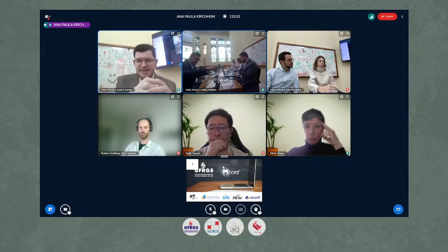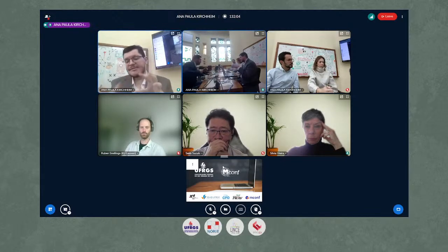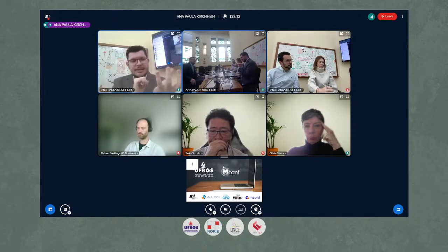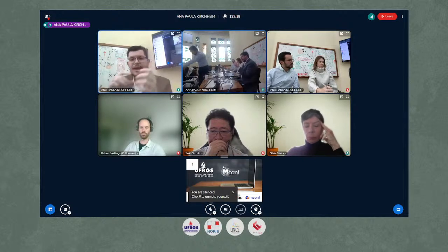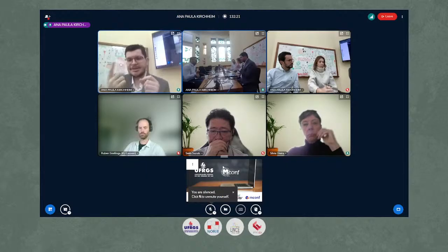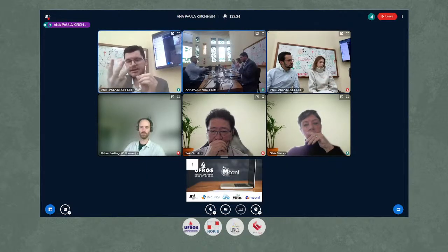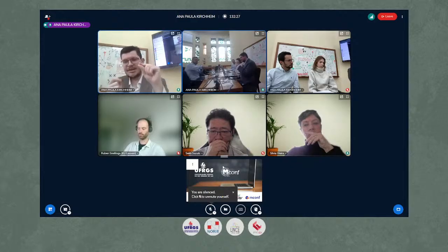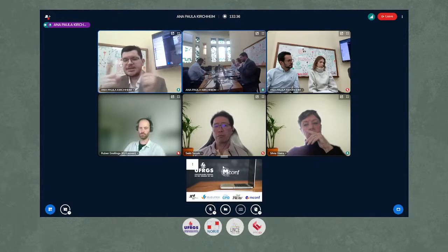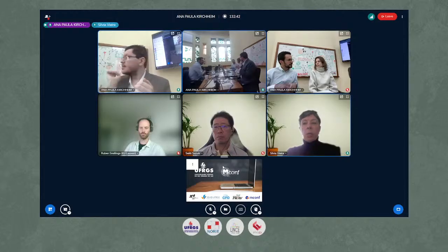So if you have less sulfate in clinker, let's take for instance a mix with 3%. If you have a clinker that doesn't have sulfate, like the white one, all of the 3% is from gypsum, so it's soluble. And you get, like, a CP that has 1.7% of sulfate. So from this 3%, 1.7 is from clinker and 1.3 is from gypsum. So what it is saying is that not all of this 3% in the cement is soluble. At least in the first 24 hours. Yeah.